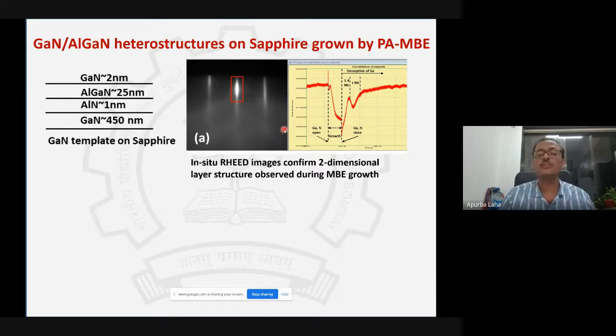Now, how much metal do you need? How much gallium? You need 1 to 2 monolayers of gallium. Now, how do you figure out it is 1 to 2 monolayers? We look at this RHEED pattern or RHEED intensity. For example, the moment you start the gallium nitride growth, the intensity drops because of the disordering on the surface. This is a specular beam. Again, remember that this is not the total intensity that we are talking about; it's just the intensity of the specular beam, which is shown here in this case.